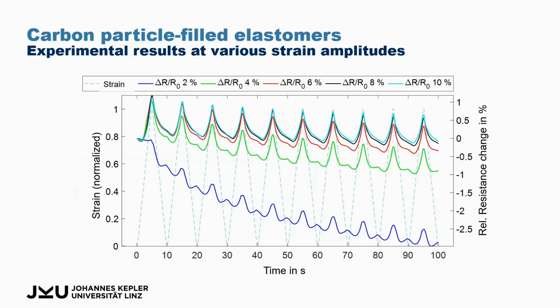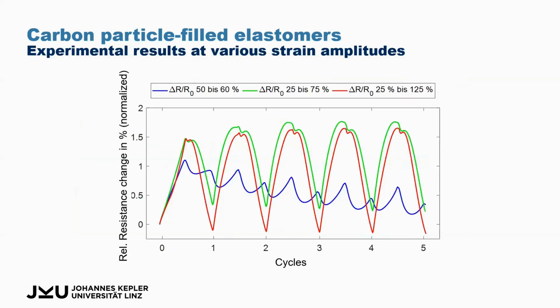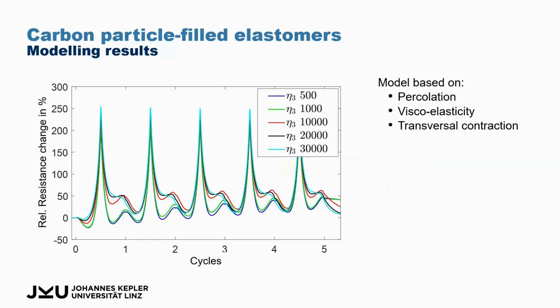And depending on strain amplitude, you even get a secondary peak at 0% strain, or at, let's say, your lowest strain level in a cyclic application. The material can show all these phenomena at different strain levels. So we assume that the underlying phenomenon is the same for the shoulder phenomenon, high secondary peak, low secondary peak, and this bunny ear. We developed an equivalent circuit model. So these are not experimental curves, but simulated curves, which can emulate this behavior. And if we change the viscoelastic properties, we see a conversion from the lower secondary peak to nearly a monotonic shoulder phenomenon.